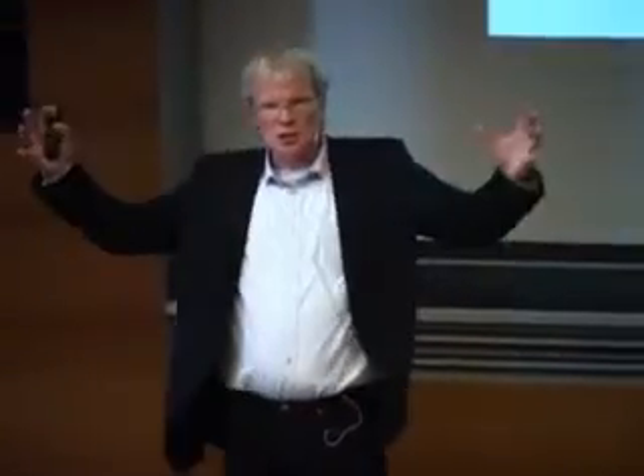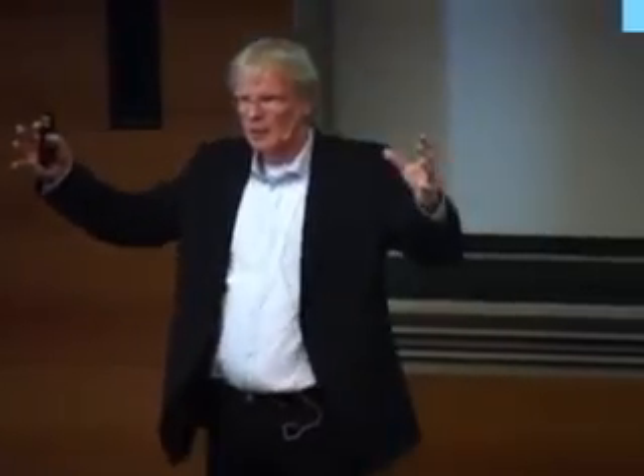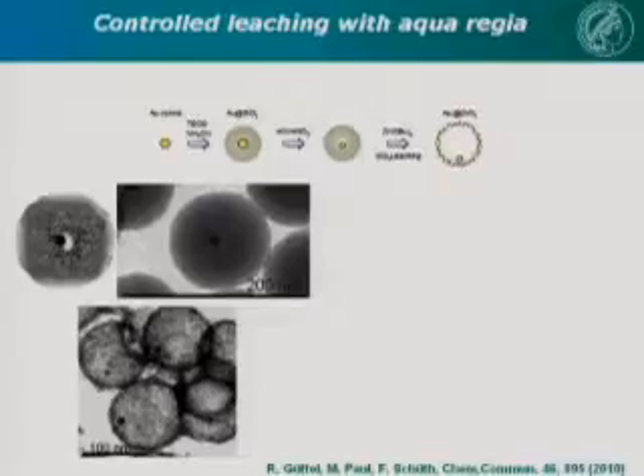We can shrink the sizes and or expand the sizes, but we also wanted to decrease the size of the gold core, not just of the zirconia shell, but also of the gold core. And the first idea you come up with is, well, why don't we partly leach out the gold by just dispersing it in aqua regia, which leaches the gold? Well, you can do that. Here you see dispersed in aqua regia, size reduced by a factor of 2.